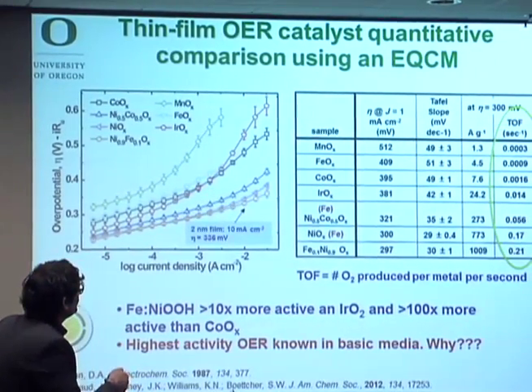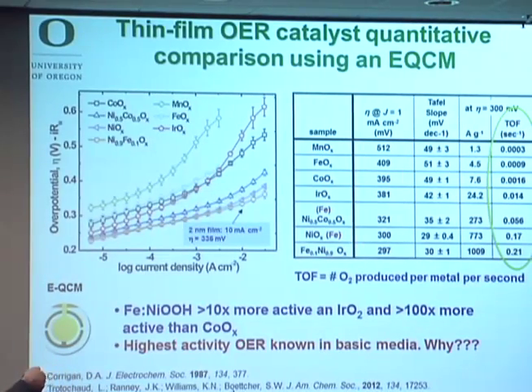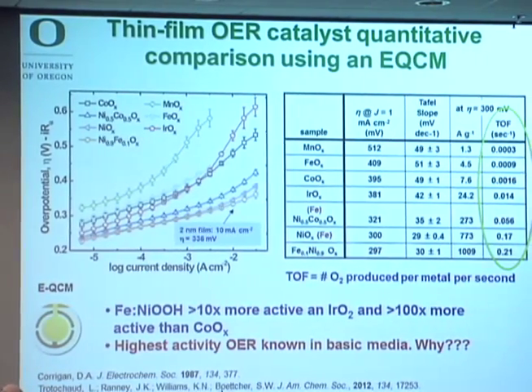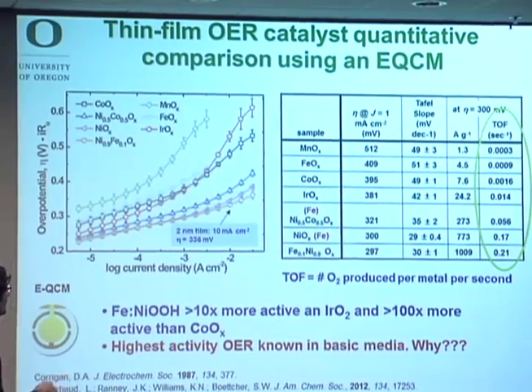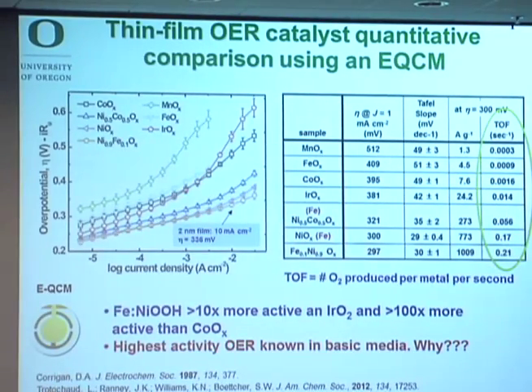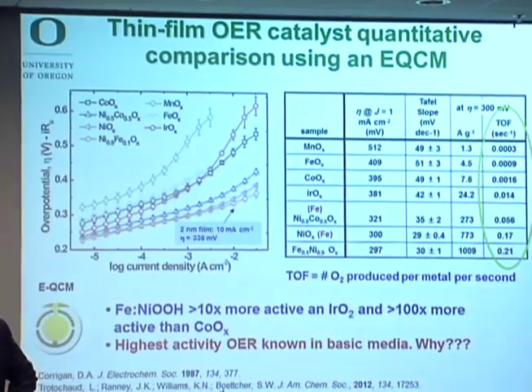on a turnover frequency basis, so it's an intrinsic measurement of activity based on the total number of metal ions at a given driving force, that are significantly higher, an order of magnitude higher than the precious metal materials at the top of that pyramid. In basic media, we've looked all through the literature, these are the fastest OER, oxygen evolution catalysts out there, these nickel iron oxyhydroxides. They're much higher than iridium oxide and much better than pure cobalt oxide. And so we wanted to understand this. This is where it starts to get really interesting.